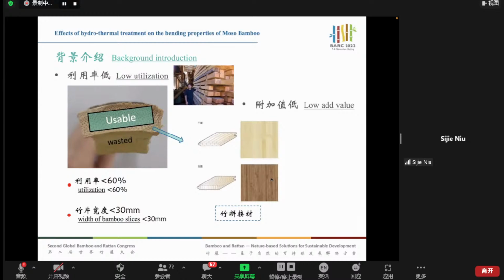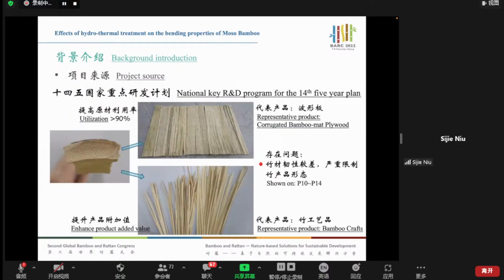Low utilization ratio is partially due to the structure of the bamboo per se, because unlike timber, it cannot be cut into large DBH timbers. It can only be combined together as an engineering material. So based on different diameter, it can be sliced into different parts. Only small proportion can be used, and a lot is wasted. The utilization ratio is less than 60%, and the width of bamboo slices is less than 30 millimeter. So we can only use bamboo materials to produce flooring and vehicle floors, very low added value.